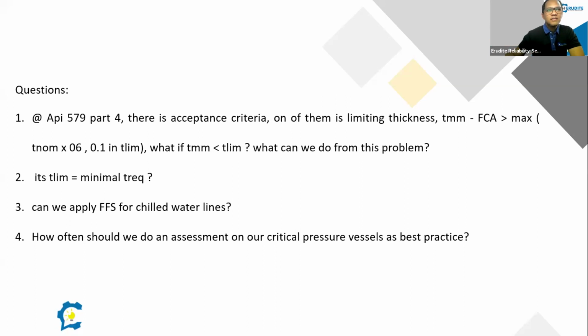Yeah. He was asking about the acceptance criteria in part 4 of 579. What he's asking about is there's a requirement that no matter how the calculations turn out, the minimum measured thickness that you have is greater than this limiting value. What the limiting value turns out to be is, I think, 0.2 of your original thickness, 0.5 of your minimum thickness, or 1/10 of an inch.